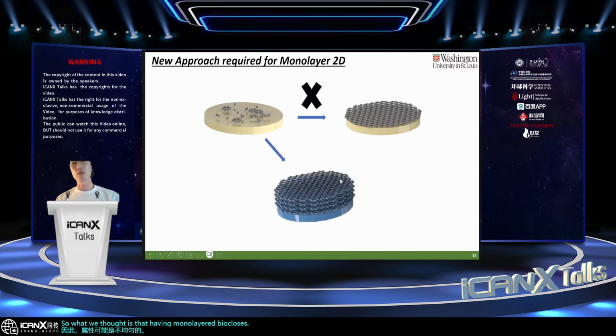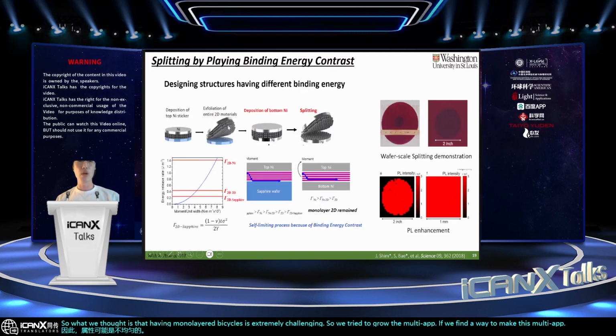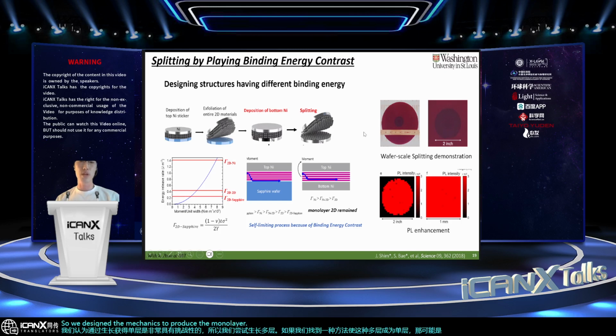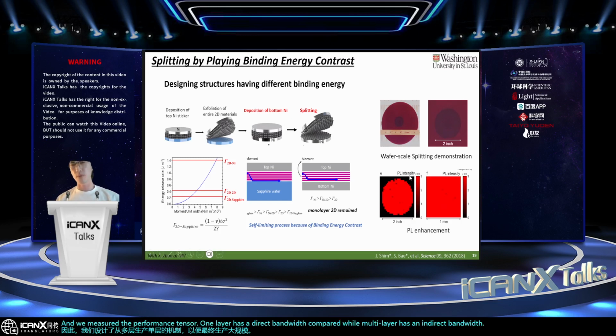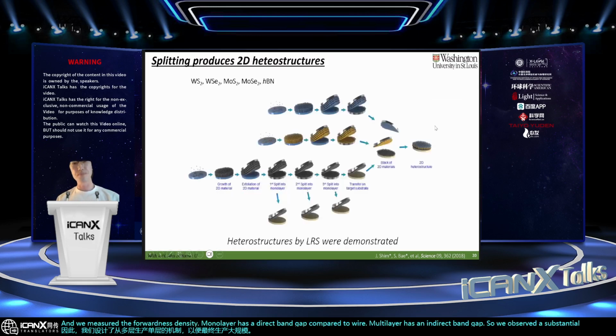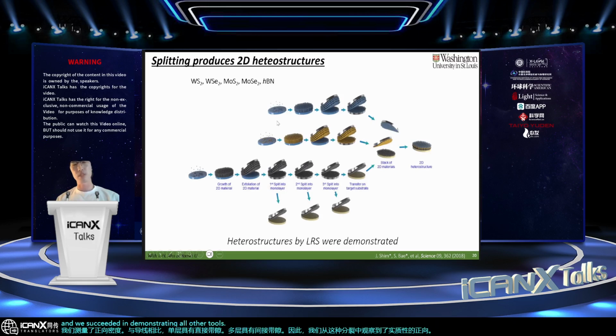So if we find a way to make this multi-layer into monolayer, that could be a good solution. We designed a mechanism to produce monolayer from multi-layer, so that eventually we produce large scale, wafer scale monolayer 2D material. And we measured the fluorescence. Monolayer has a direct band gap, while multi-layer has an indirect band gap, so we observe a substantial fluorescence boost from this split 2D material. And we succeeded in demonstrating this on all other 2D materials using this splitting technique.